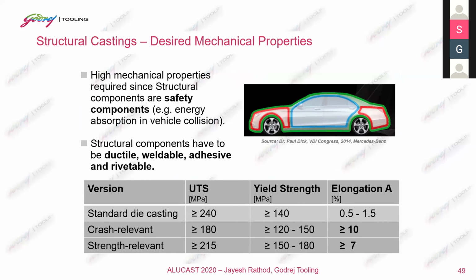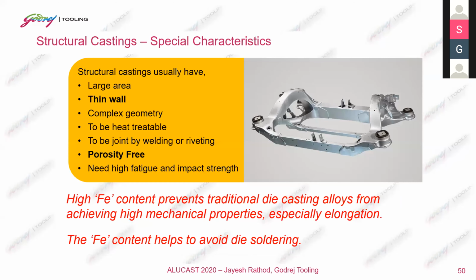The structural casting alloys are actually characterized by higher elongation ratios. Currently, the elongation ratio is 0.5 to 1.5, as you can see here, but with crash relevant and strength relevant parts, it should be more than 10% and 7%. So we should understand the specific characteristics of structural alloys.